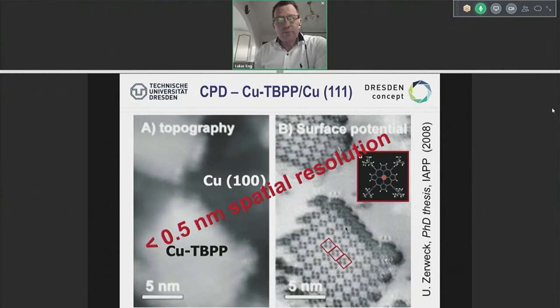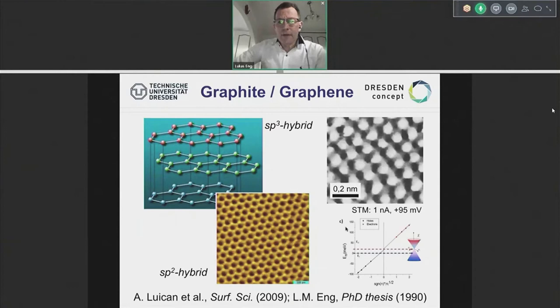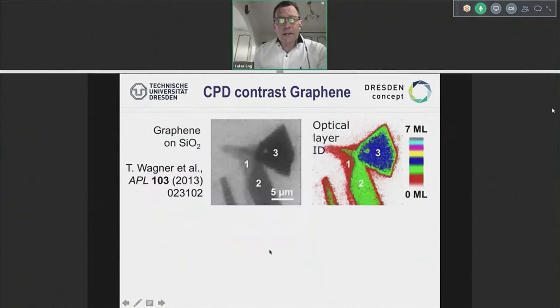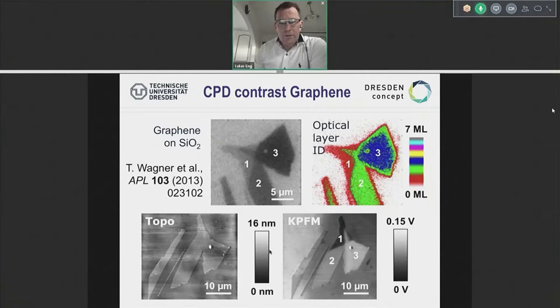Last example, graphene. Graphene is a very modern type of material where we have really the graphite surface. And if you clear this off, you see here an STM image of an SP3 hybridized, and an STM image of an SP2 hybridized. What you can see basically with your contrast in CPD in Kelvin is the fantastic layers 1, 2, 3 of these different graphene layers. You can nicely see 1, 2, 3 layers in the optics as well.